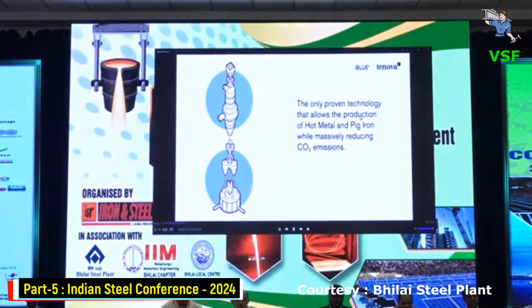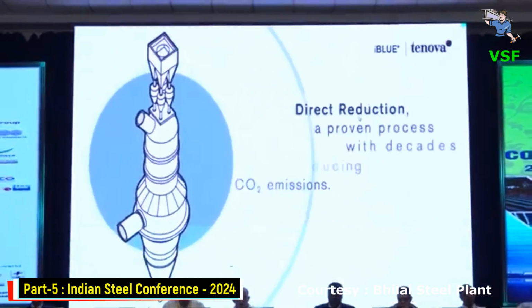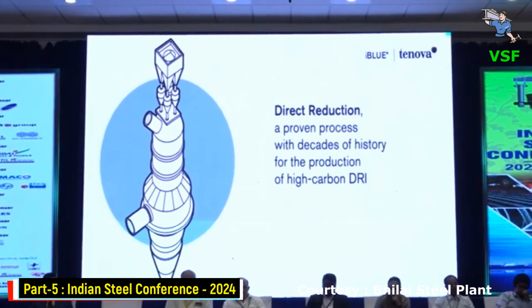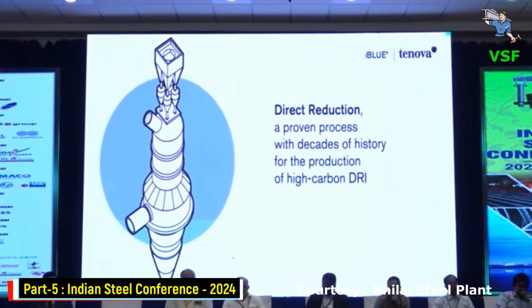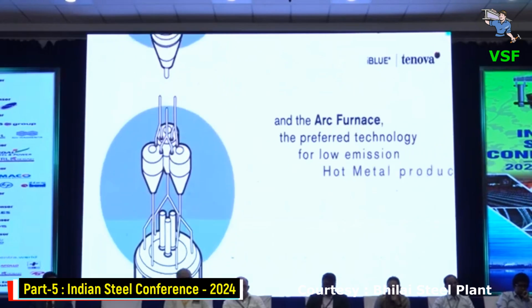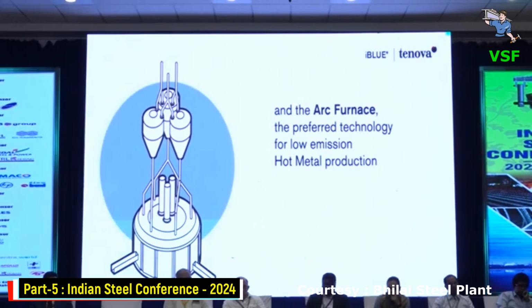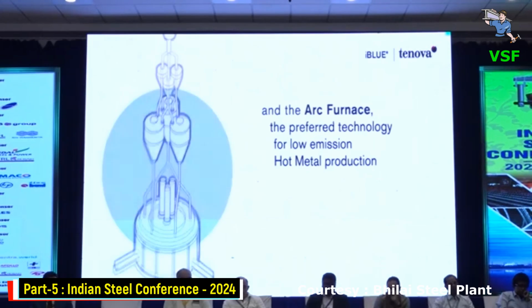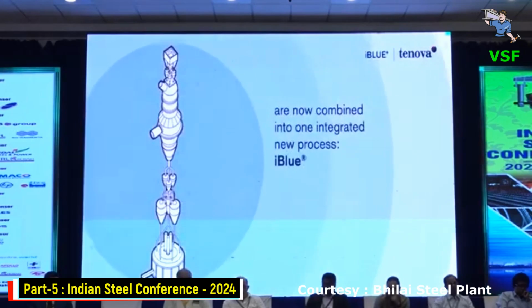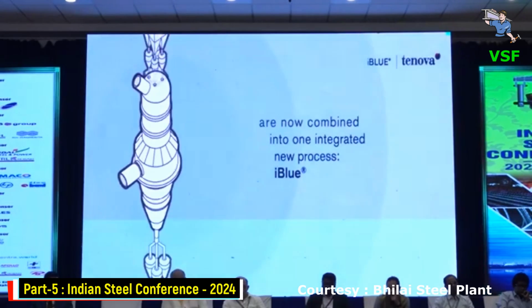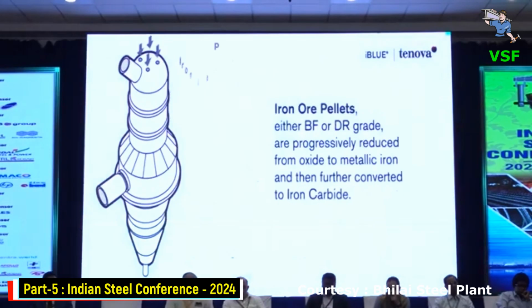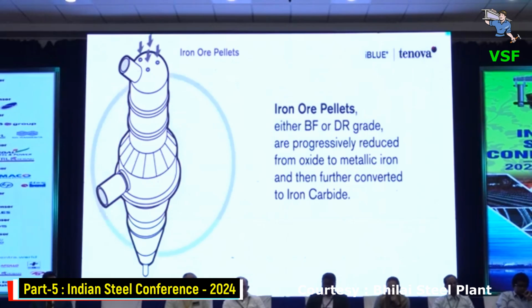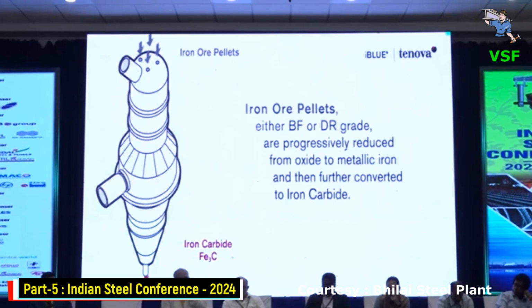Reducing CO2 emissions. Direct reduction, a proven process with decades of history for the production of high carbon DRI, and the arc furnace, the preferred technology for low emission hot metal production, are now combined into one integrated new process, iBlue. Iron ore pellets, either BF or DR grade, are progressively reduced from oxide to metallic iron, and then further converted to iron carbide.